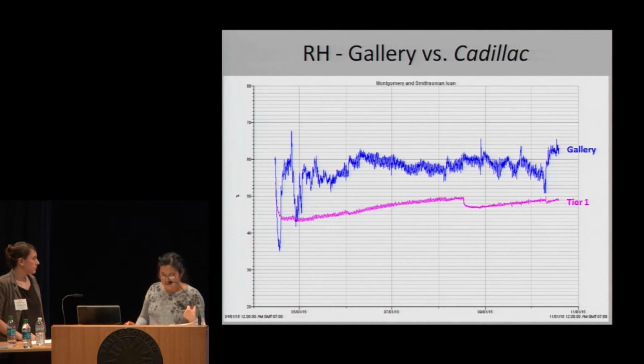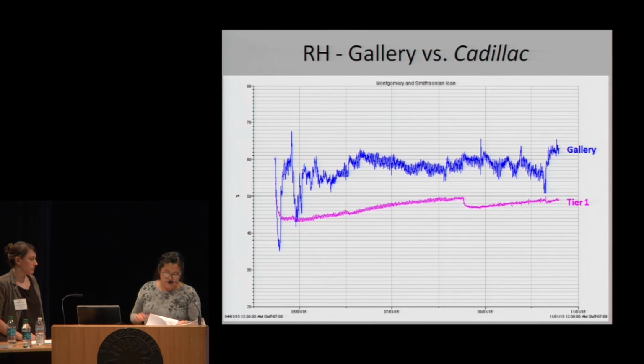And this is a close-up of the Cadillac case through the run of the show, for the entire run of the show through October. Regarding the replenishment of the activated carbon, we don't have a dosimeter, but we placed A-D strips as well as copper and silver coupons into two cases to serve as a bellwether for how the carbon was performing. And we didn't see any visible change so far, so thus far we feel satisfied with the performance of the amount we put in.